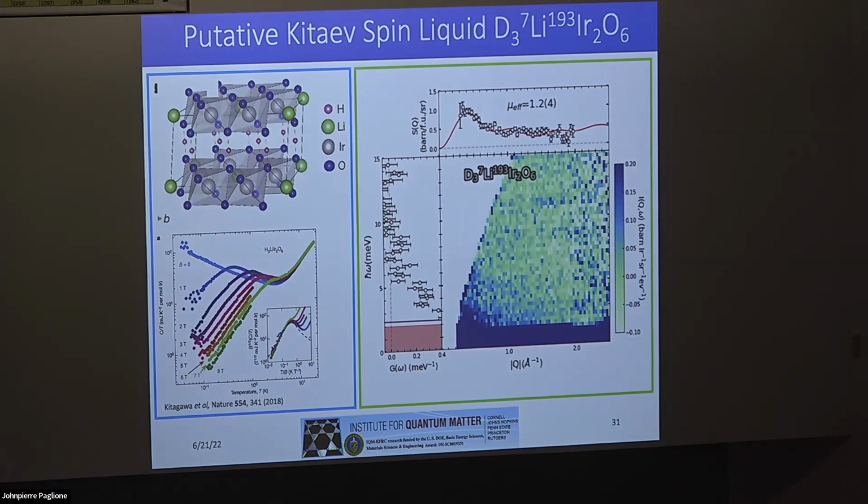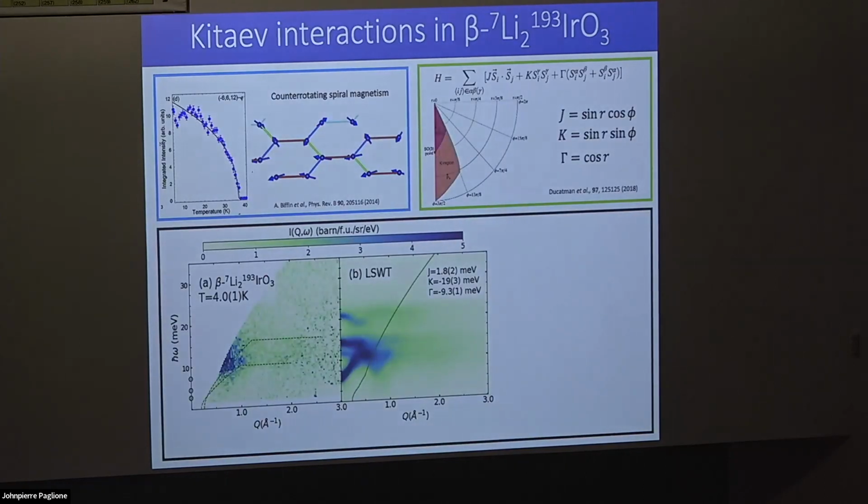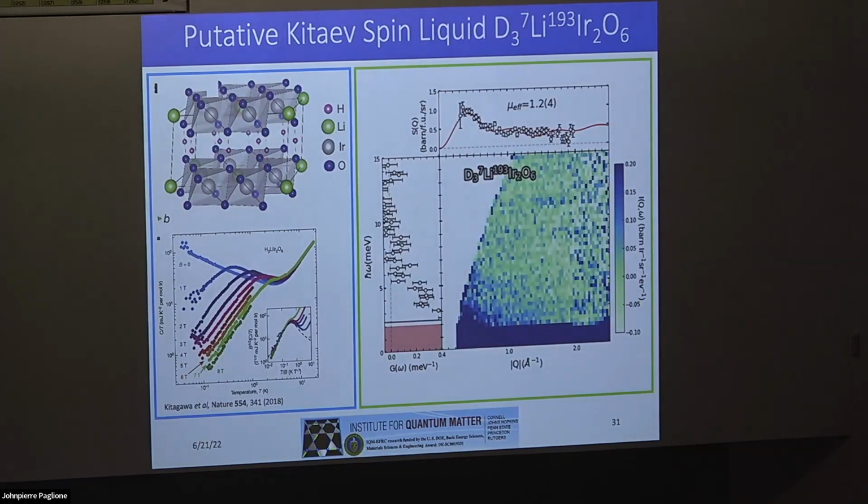It's quite different actually from the case of the ordered magnet. So we really can see a distinction between the ordered system with anisotropic interactions, a gap in the excitation spectrum as we expect for the ordered system. But in this quantum spin liquid candidate, consistent with the power law specific heat, etc., we do have what seems to be a gapless excitation spectrum, and we can measure the momentum and energy dependence of that. Clearly there's not that much information to get from these kinds of data.